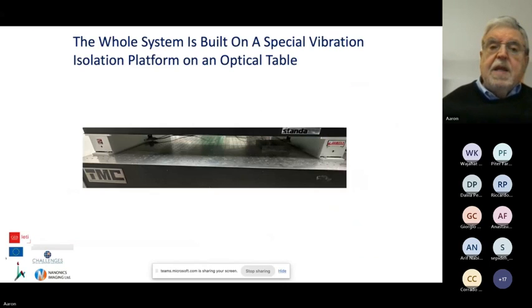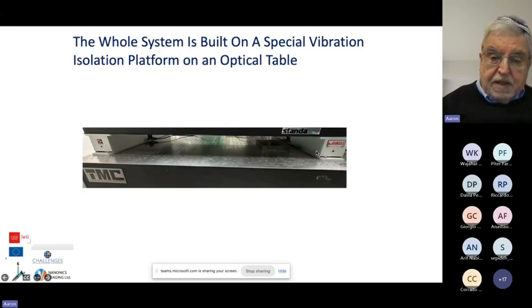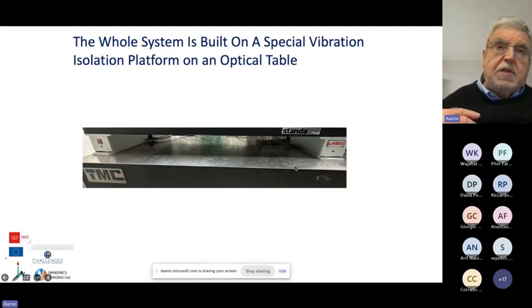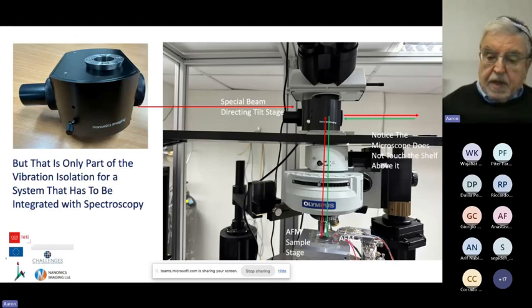Now, the whole system has to be really isolated. The first isolation is vibration isolation. The vibration isolation does not come from the optical table. The optical table is a pretty bad thing because it gives you lots of low frequency, it amplifies building low frequency vibrations. So on top of that is sitting an active table on which there's a breadboard and on which the entire system is built. So the system is built on that table, okay? It has the optical microscope as we described. It has the AFM. It has the stage.